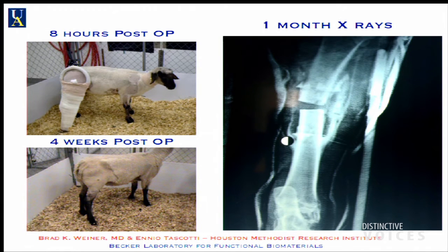whatever that might be. And so we were excited that we put this crude-looking splint on here, which is a cast with a piece so that he couldn't sublux. 8 hours after surgery, the sheep could stand up. Okay, 4 weeks later, we cut it off, and it's strong enough that he can run around the field. And if you didn't have his leg marked, or tattooed, what they did, you'd never know, you couldn't tell which leg it was. Now, when we did 1-month x-rays, and this was just done last spring, the bone didn't go through the tube, so we didn't look very smart.